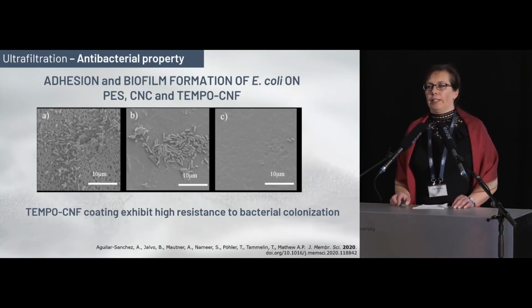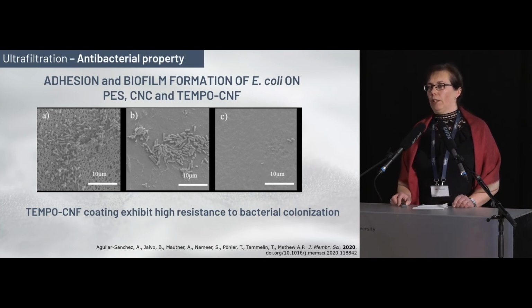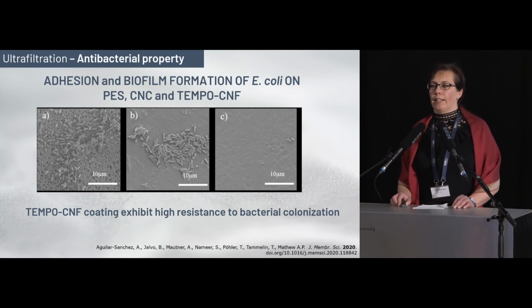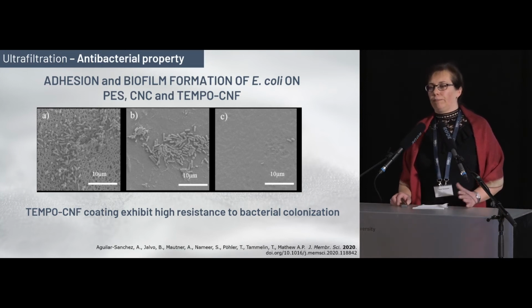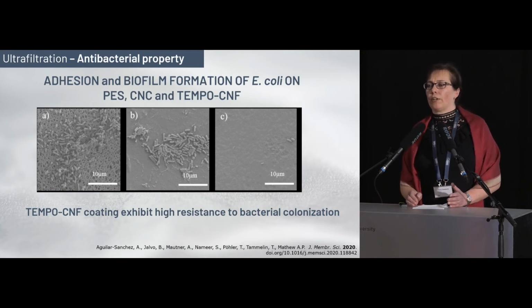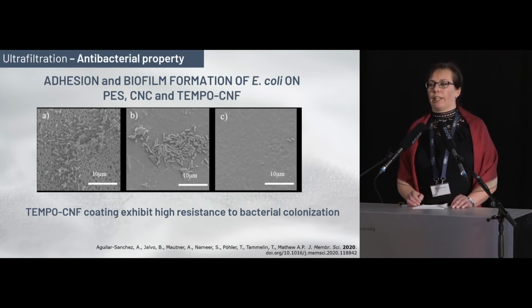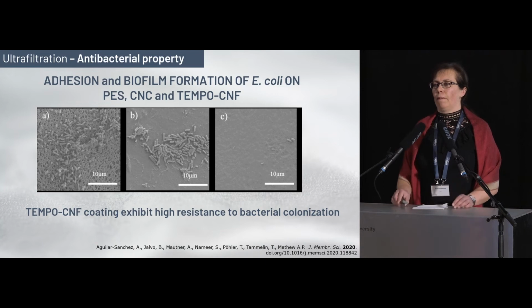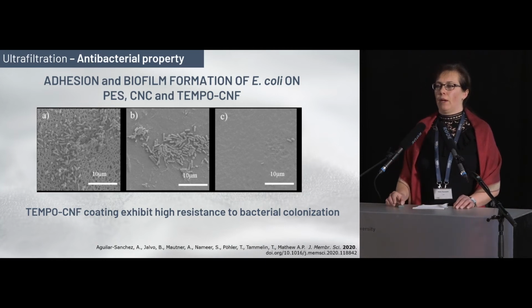We also studied, with similar membrane materials, the adhesion and biofilm formation of E. coli bacteria. These SEM images quite straightforwardly indicate that on the PES membrane, the bacteria are really colonizing the surface. But on this TEMPO CNF surface, you can see that there is no E. coli detected on the surface.